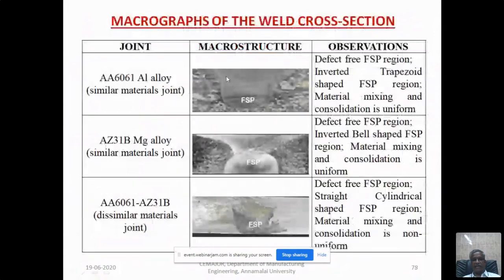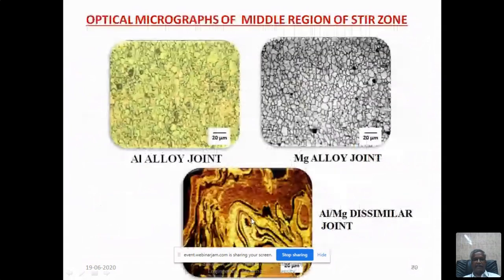So this is the macrostructure in similar welding, aluminum with aluminum. You see an inverted trapezoid shaped friction stir processing zone. Here it is a bell shaped friction stir processing zone in the magnesium alloy. In the dissimilar joint, aluminum with magnesium, you see a straight cylindrical region, and I'll show it in the magnified view. Mixing takes place, but layer by layer. Aluminum with aluminum and magnesium with magnesium are similar, but in the dissimilar joint you see an intercalated microstructure.